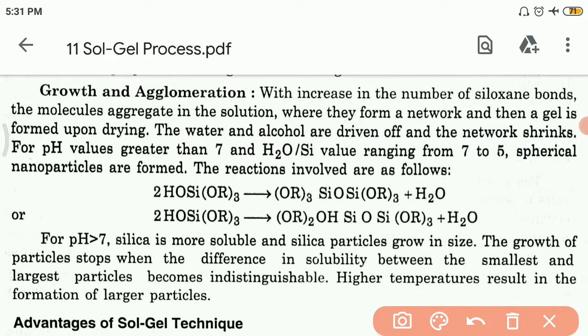So for pH value greater than 7 and H2O to Si value ranging from 7 to 5, we will have spherical nanoparticles. Okay, and the reactions involved are as follows. Now for pH value greater than 7, silica is more soluble and silica particles grow in size. The growth of the particles stops when the difference in the solubility between the smallest and the largest particles becomes indistinguishable. Higher temperatures will result in the formation of larger particles, right?